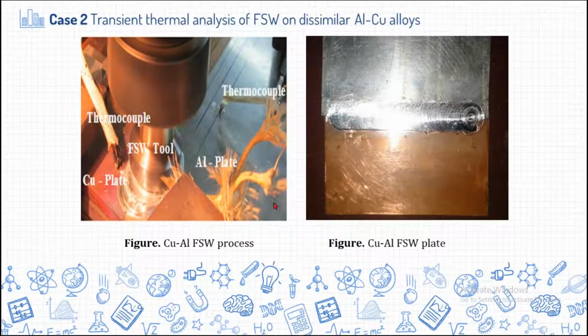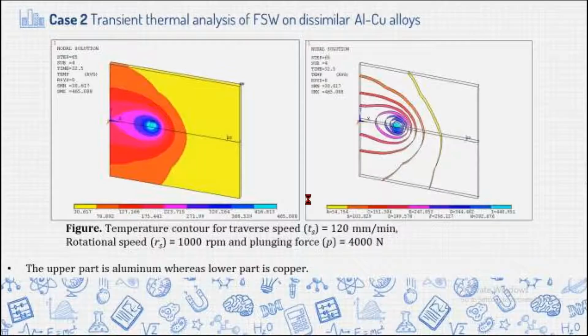So we weld like this, but in this simulation, the bottom plate is a copper plate and the top plate is an aluminum plate. If we see this, we kept some offset of the tool. That means almost 2/3 of the area of the tool pin is concentrated on the aluminum side, and only 1/3 of the area on the copper side.